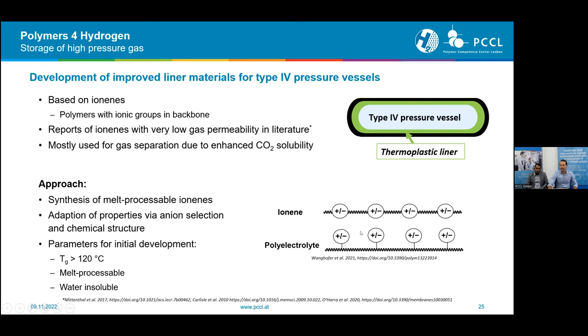And there is another term that you might also know, ionomers. They are also ionic polymers, of course, but they have a rather low concentration of the ions directly in the structure. In literature, those ionenes are usually used for gas separation because the ions improve the solubility of CO2 gas, and it has a good selectivity towards those. There are reports of those ionenes having very low gas permeability, even though for those membranes they try to increase this permeability. So that seemed very promising for us.